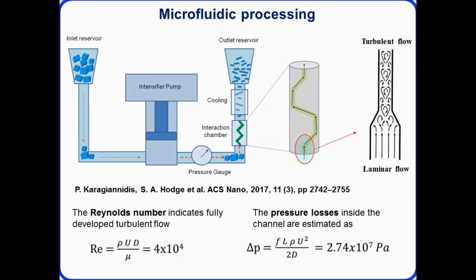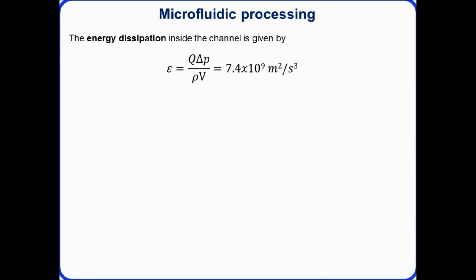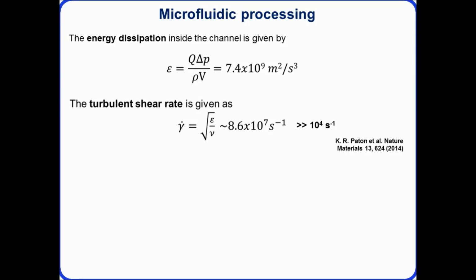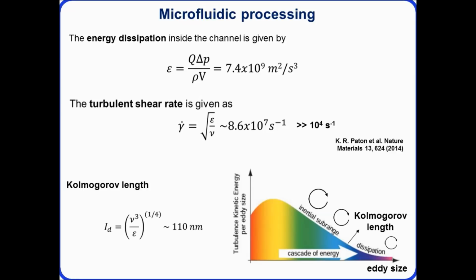We can also, with the help of microfluidics, work out some of the other key parameters, such as the pressure losses. We've also looked at the energy dissipation through the channel, and the most important characteristic is the turbulent shear rate. We have a value here which is on the order of 10^8 per second. Some previous work on graphite exfoliation showed that you need around 10^4 per second to actually start to peel away layers of graphene from the graphitic structure. So we have a lot of room to play here in terms of looking at other materials that might require higher shear rates to perform exfoliation. That's quite key for the microfluidic process, to have this extra room to play.